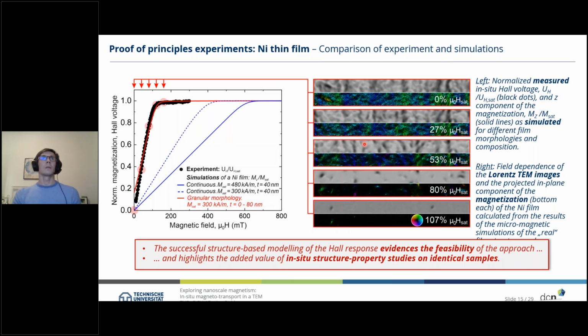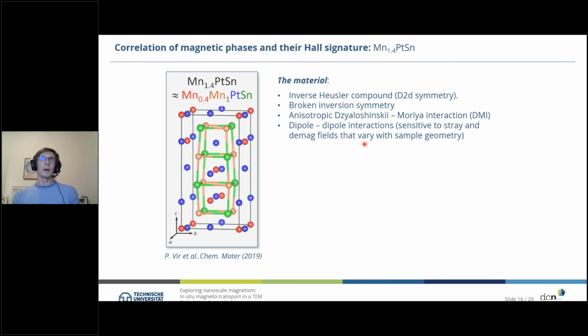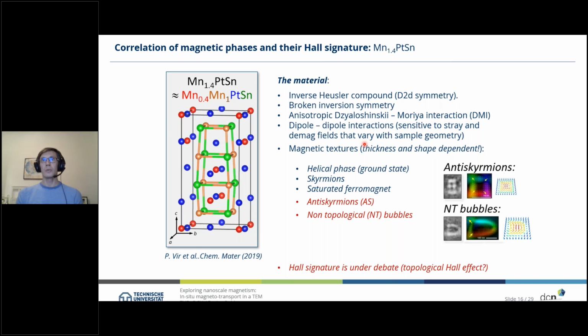So with this knowledge and the proof that our setup is working quite well, is very powerful, we wanted to start a second system, the inverse Heusler compound manganese platinum tin, where you can see here on the left hand side the crystal structure, and it has a broken inversion symmetry and therefore an anisotropic Dzyaloshinskii-Moriya interaction. And now, due to the dipole-dipole interaction and with varying sample geometries, we have a very large zoo of different magnetic textures which appear in that material, starting from the helical phase in the ground state to skyrmions at lower temperature. It's of course a saturated ferromagnet for high magnetic fields, and at room temperature.